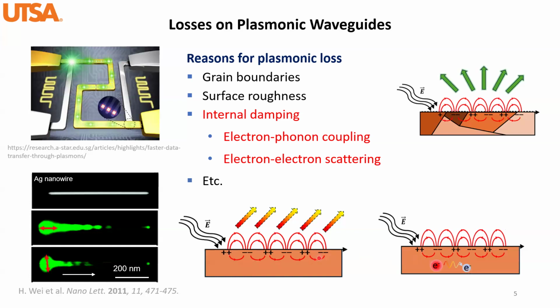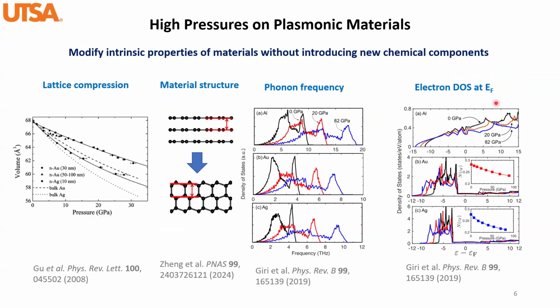And these two are intrinsic properties of the material, which are hard to mitigate under ambient conditions. But for grain boundaries and surface roughness, you can always improve them or mitigate their impacts by, let's say, improving the chemical synthesis methods or the nanofabrication technique. So that's why this problem just remains there in the field. And so when I started my independent research, I thought, okay, let's try to tune these intrinsic properties of the material using high pressures and see what will happen.